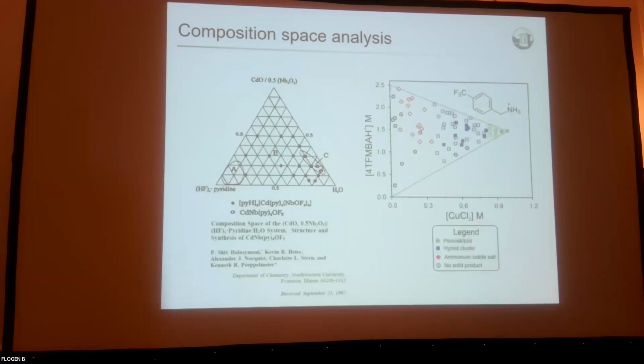For our system, this is what it looks like. Instead of plotting the outcome of the experiment as a function of mole fraction, we plot the outcome of the experiment as a function of the concentration of either the ammonium cation or copper chloride. Then we can see that certain types of compounds dominate the crystallization in different regions, and of course the concentrations of our corners define the concentration space in which we can work. So we want to push them out as far as we can.